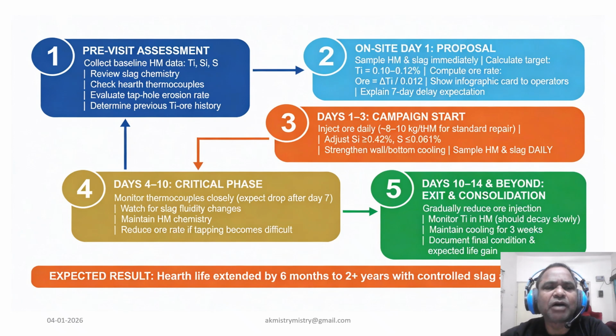We wrap up with our operational roadmap. We start with a pre-visit assessment to collect baseline data. By days 1 to 3, we begin daily ore injection and strengthen cooling. Day 4 to 10 represent the critical phase where we monitor thermocouples for the expected temperature drop, and this is supposed to be one of the most intensive exercises to be conducted by our blast furnace operation team. Finally, after day 14, we gradually reduce ore injection, ensuring the layer stays consolidated for long-term hearth protection.